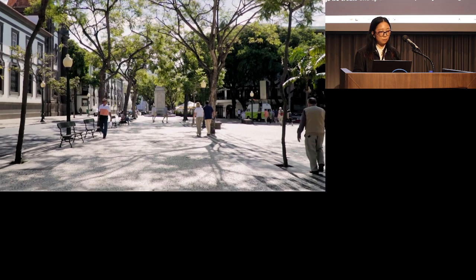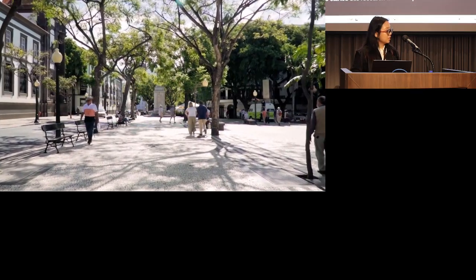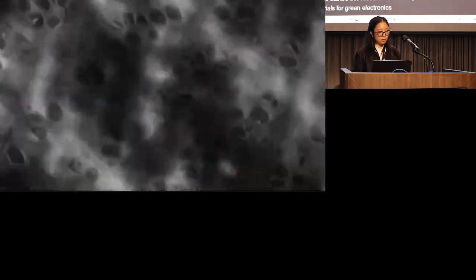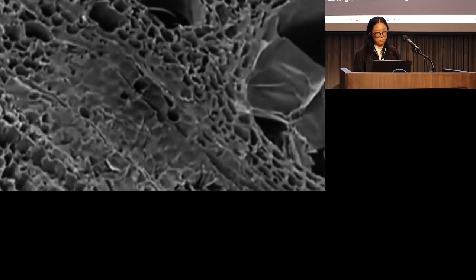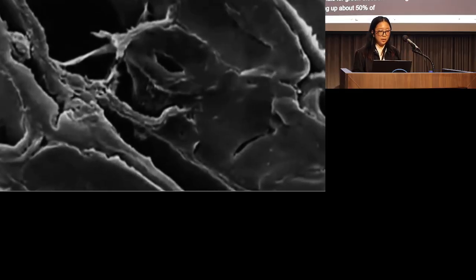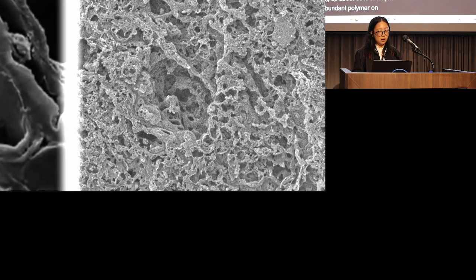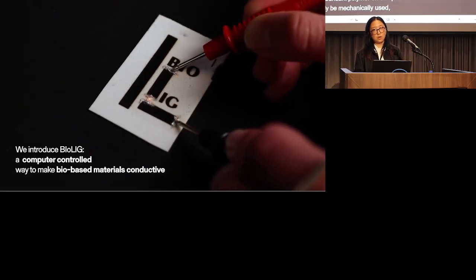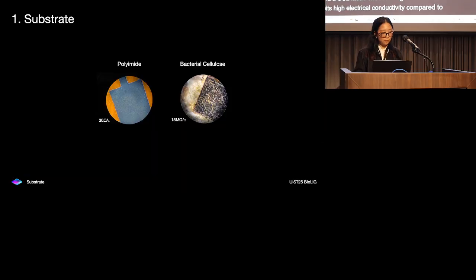fabrication tools? Making up about 50% of all plant matter, cellulose is the most abundant polymer on this planet. The fibrous strands of cellulose can not only be mechanically used, but can also be graphitized into porous graphene via a CO2 laser. The resulting laser-induced graphene, or LIG, exhibits high electrical conductivity compared to other carbon conductors, and the fabrication process is computationally controlled, allowing for precision and repeatability. So first, we want to talk about the substrate.